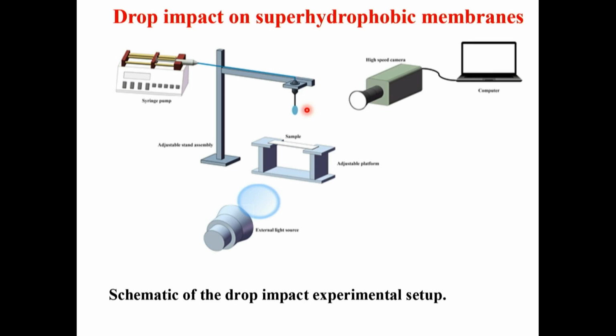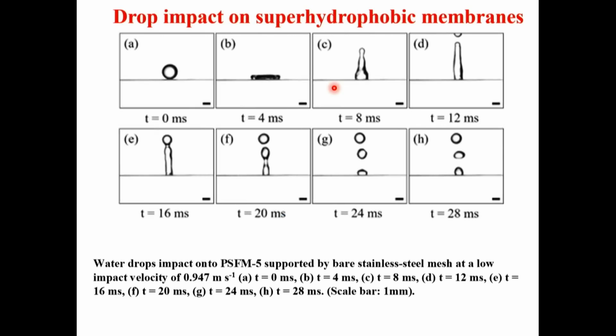Now, the membrane by itself is supported by a stiffer support, as is usually done, but the stiffer support has much wider pores, so for penetration purposes it means nothing. So the support is just mechanical, not to break the membrane when a droplet impacts it. And the main hydraulic resistance is coming from the very thin layer of nanofibers which we made on top. So this is the experiment, and it allows us to observe penetration directly through CCD camera recording.